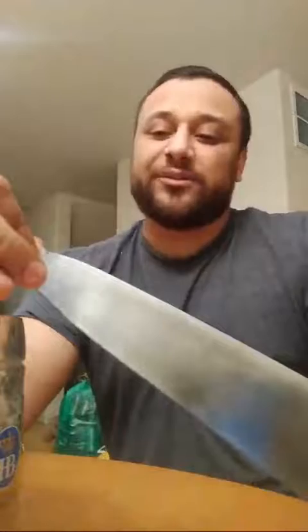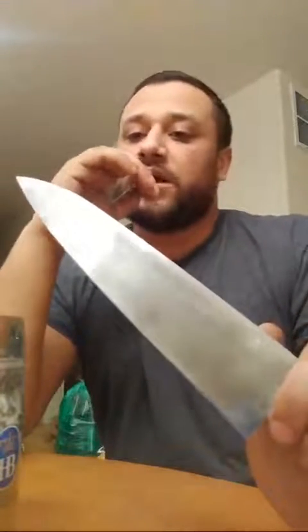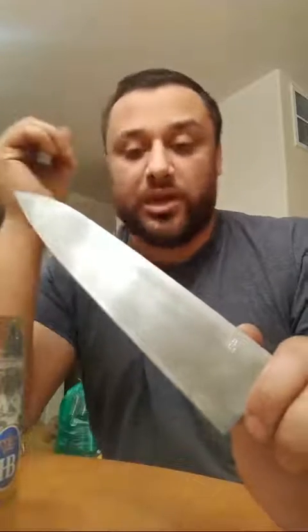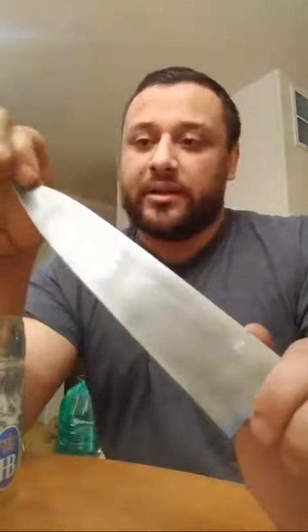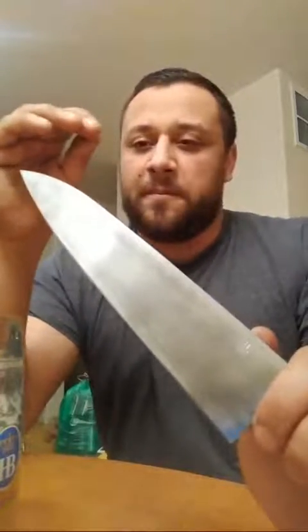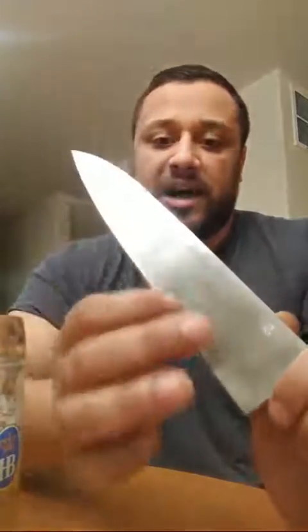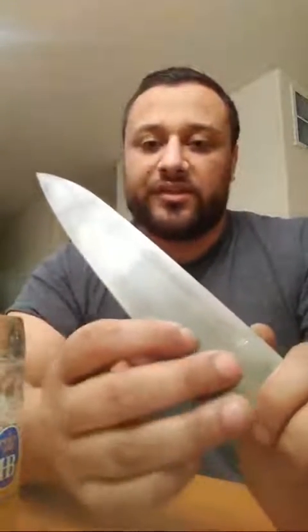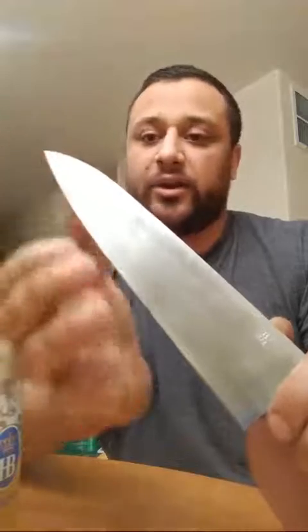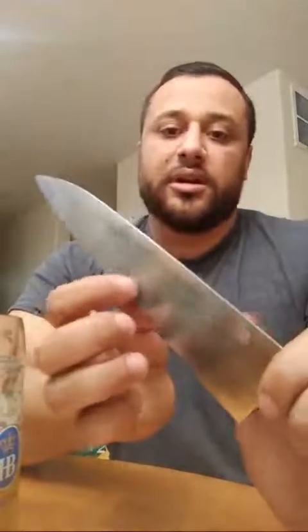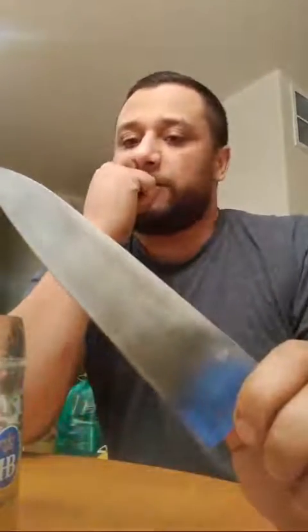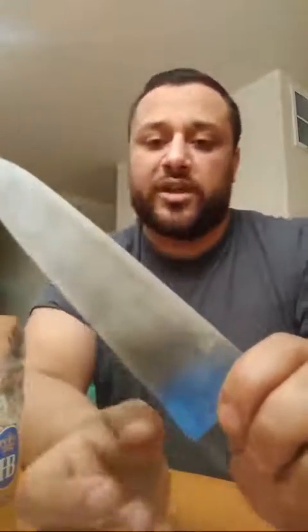But the hard chroming I thought was really cool, because essentially you take something like a tool steel, which will rust as you look at it if you leave water on it, and you coat it in hard chrome, and now you basically have a high-tech steel with a stainless jacket on it, and it'll only rust at the edge.